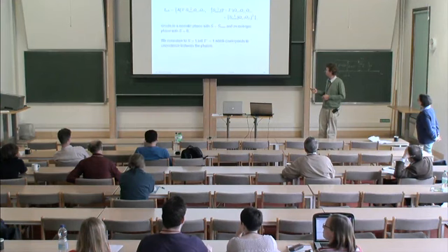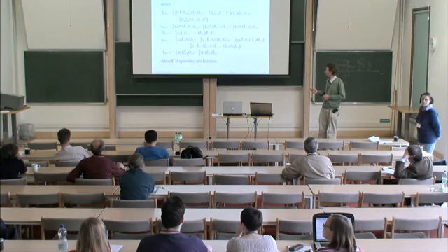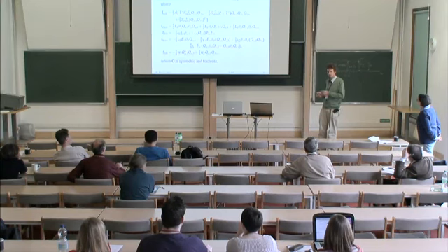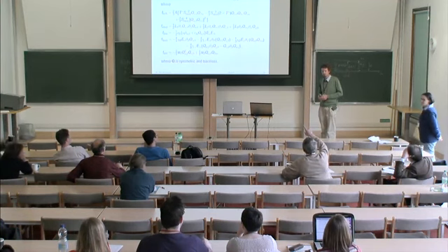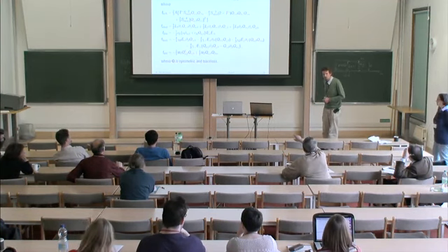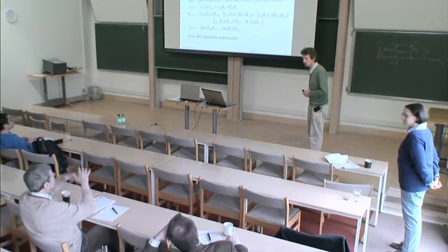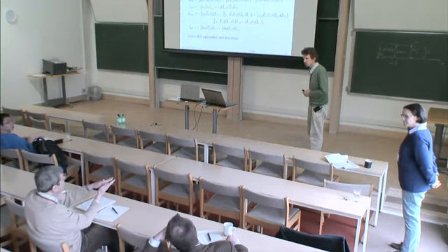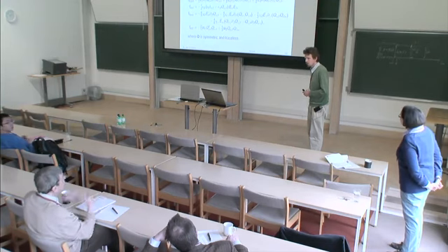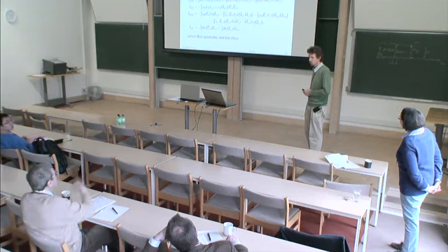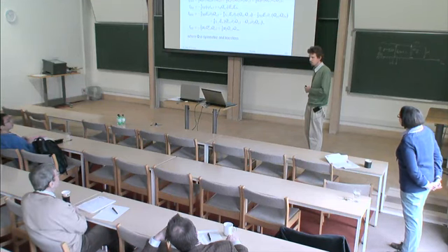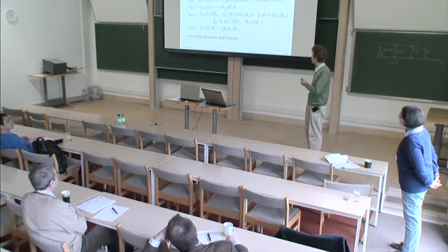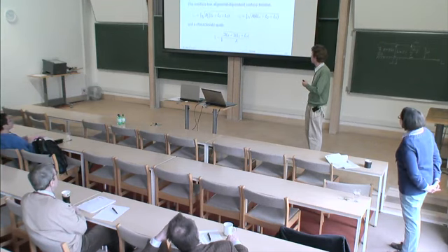If we wanted to discuss a free surface, then what we would need to do is put in another order parameter, a binary phi parameter, and then couple the nematic and isotropic to that, and that would give us more freedom. Your wetting term has something to do with orientation only. I said it's related to surface tension. There is surface tension just proportional to area. Yes, so that comes naturally out of the treatment. Yes, these are the effective surface tensions.